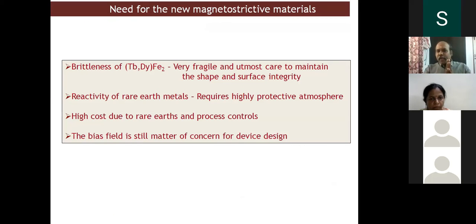But although this magnetostrictive material I talked about, particularly this TbDyFe2 material, is a good magnetostrictive material which shows high strain, there are some problems in this material. The materials are very brittle. For example, if you just tap it, the material will break. In terms of mechanical behavior, the UTS is only 28, so it is very brittle and very fragile, and utmost care has to be taken.